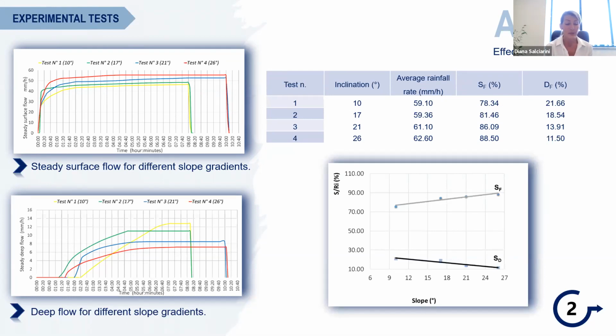This graph shows that as the slope inclination increases, the steady surface flow increases, and consistently the steady deep flow decreases. And we could find a relation between the steady surface flow, the steady deep flow, and the inclination under the same rainfall intensity.